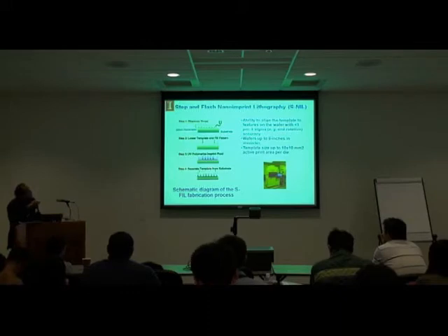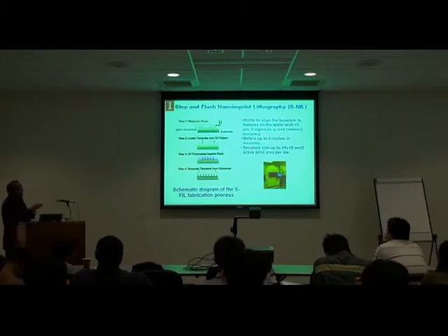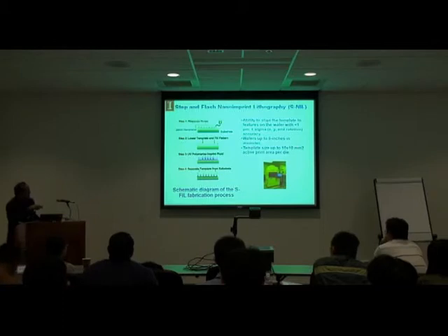So what you do is you dispense a bunch of drops. There's a system that dispenses small drops on the surface, and then there is your master, which you make separately, and this master now is in quartz. So it's a quartz transparent mold, and you define your features on that first. Then you lower this template and fill that pattern, and then through this transparent mold you shine UV light and you polymerize your resist, and then you separate the template from the substrate, because now it's not liquid anymore, it's been polymerized. And this now becomes your photoresist to do etching or other subsequent patterning.